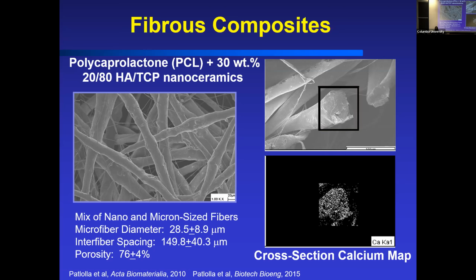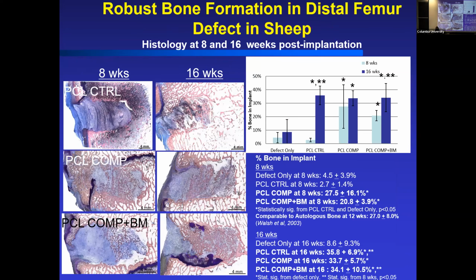So we created this fiber composite, polymer and ceramic. Ceramics are built into the fibers with these nano ceramics. And we've been able to demonstrate now in a number of different models. This just is in the sheep animal model that we're getting pretty robust bone formation. And this is using the material by itself or in combination with bone marrow. So we can load bone marrow, which has those stem cells, and we also get this robust bone formation or integration into those defects.